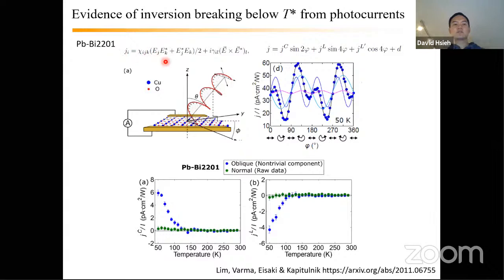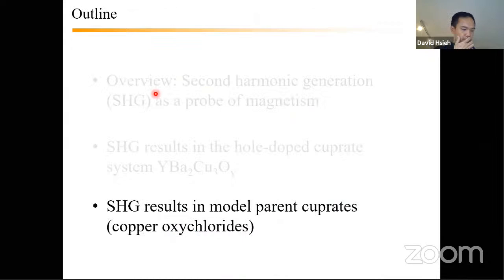And you can do similar things in this type of measurement that we do, where you do rotational anisotropy, for example, and you start to tease out the structure of the tensor. And at least in these bismuth 2201 materials, and 2212 they've done as well, they also see evidence of inversion breaking below T star. Okay, so this type of phenomenon seems to perhaps be present not just in YBCO. Now I want to finish by going into some more recent results on copper oxychlorides, and this is some mysterious data.